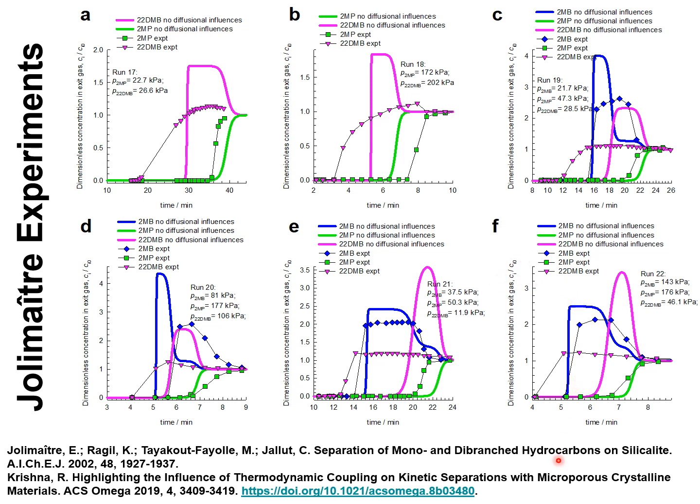And this is also helpful in the separations because we want to recover 2,2-dimethylbutane for incorporation into the gasoline pool, and due to diffusional influences, the component to elute first and recovered in the raffinate phase is 2,2-dimethylbutane. So diffusional influences help separations. Let us demonstrate that quantitatively in the next slide.